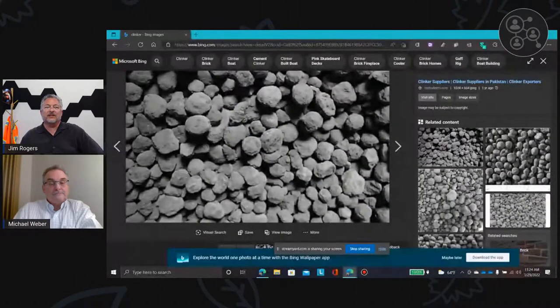Yeah, that is. That's amazing. So I'm gonna back up and see. Okay, so we're talking about cement. So just the one ingredient in concrete. And I pulled up a picture of clinker here. I assume this is clinker that Mike's talked about, that is produced as part of the cement manufacturing process. So basically, we mine limestone, we crush limestone, we heat it to 2,500 degrees. It comes out molten and eventually cools into what you see on the screen here, which is clinker. And then this clinker is ground down into the fine cement powder.